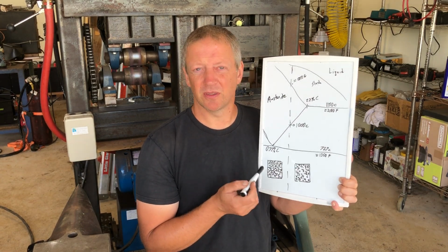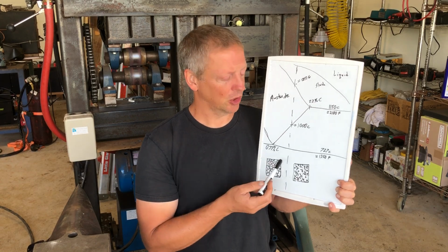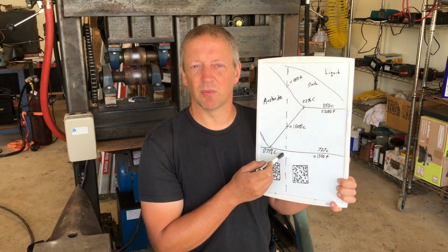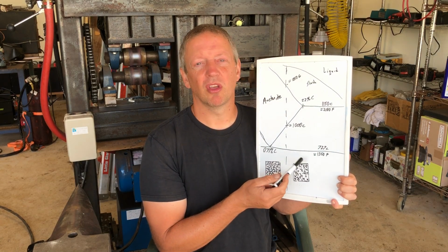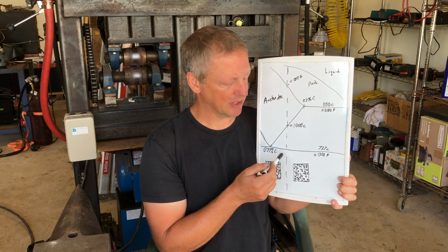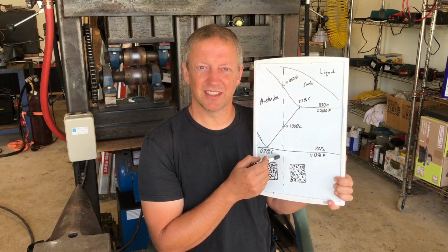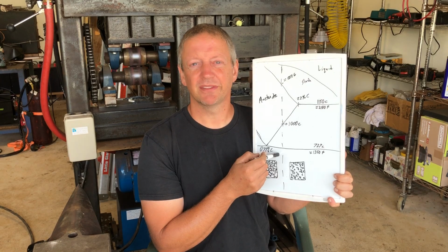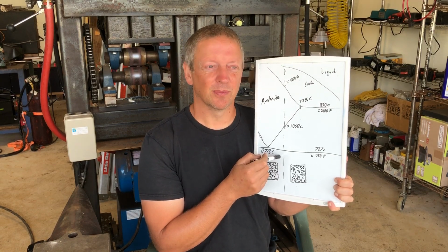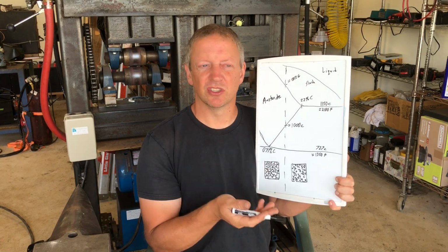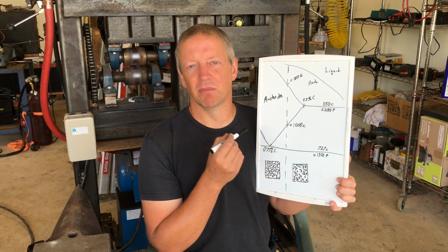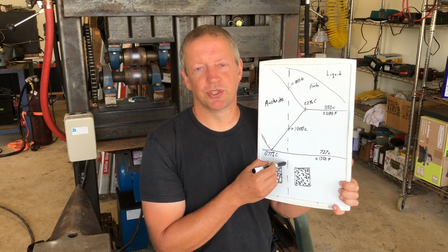I'm going to tell you, though, this is a key piece of information. You may have been told or read somewhere that Wootz needs to be forged subcritical. And I'm going to tell you right now, don't do it. Subcritical forging, not a good idea. It's one thing to do subcritical corrective forging. You're just heating it up to that very dull red, kind of a black heat, because you want to straighten something. Have at it. If you want to actually start moving the material, don't do it.